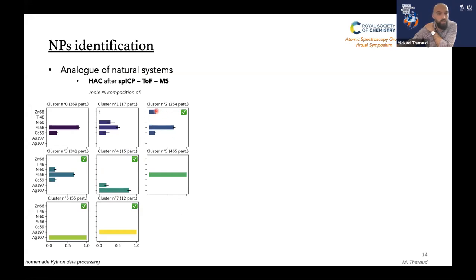Basically, you see here the three metallic particles in clusters number 2 and 3, so zinc, iron, and cobalt, and nickel, iron, and cobalt. And what is more interesting is that the composition given by the single particle TOF-MS is the right one. And here you can see also the bimetallic gold and silver nanoparticle. Again, the composition of the nanoparticles in this cluster is in perfect agreement with the one that was expected. And also the two last ones here are pure gold and pure silver nanoparticles.